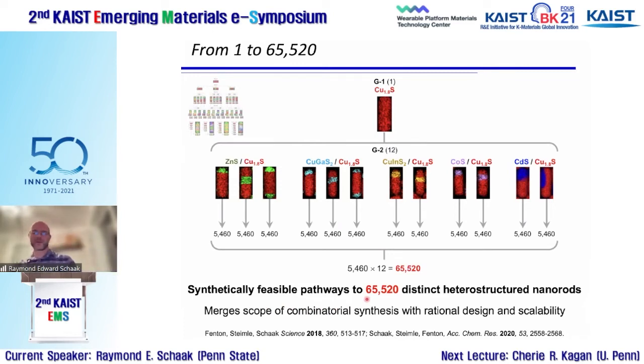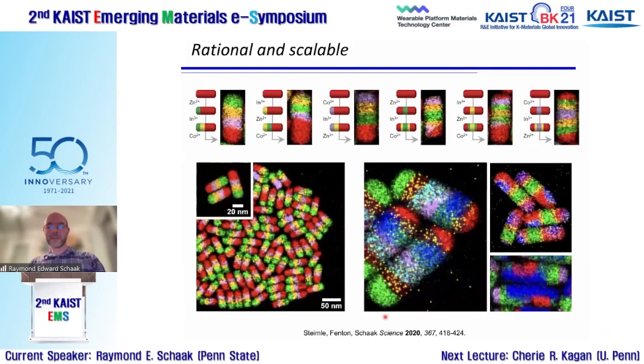So what that really does in terms of some of the original questions I posed, if a computational prediction were to come up with any of these, we have a pathway to make it. And it's predictable based on the simple relationships of what order you inject and what the crystallographic relationships would be. So it really merges, in terms of getting into the tens of thousands of possibilities, the scope of combinatorial synthesis with what you can make rationally in a lab in a way that's scalable with high yield. And just to show what is possible, this gives an idea of the particle to particle uniformity. I always like to point out mistakes, right? There's a few that overexchange, but for the most part, these are pretty uniform particle to particle in terms of what they look like.